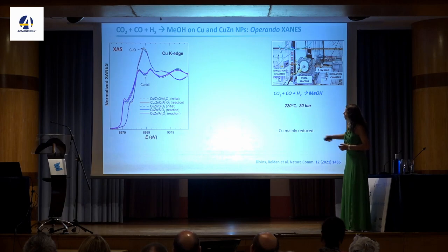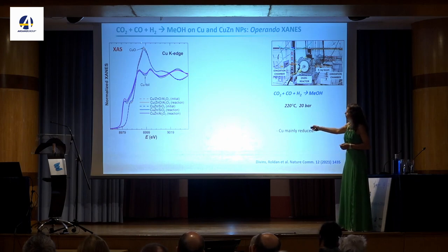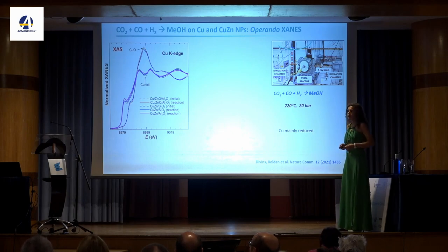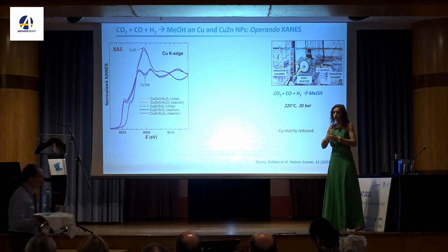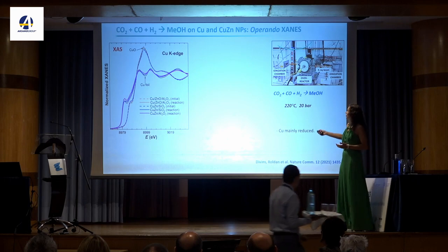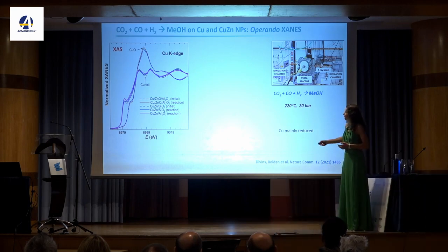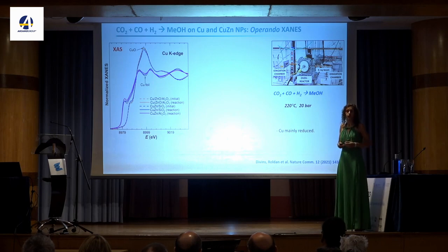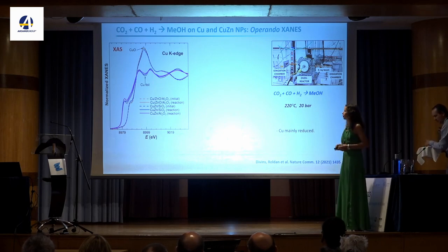And we followed the copper signal of these mono and bimetallic particles on the different supports. And you can see that when you start the reaction, on all the supports, very quickly you see almost complete reduction in the copper. Because the particle size that we had was about, in this case, 3 nanometers, even though we see that this is metallic, I cannot exclude that there is still a little bit of oxygen dissolving in the copper. That is very commonly happening. But it looks mainly metallic.